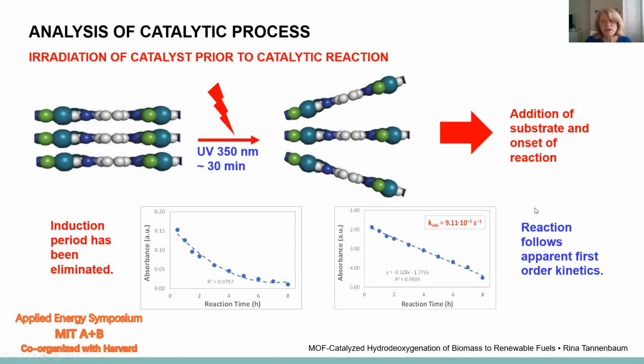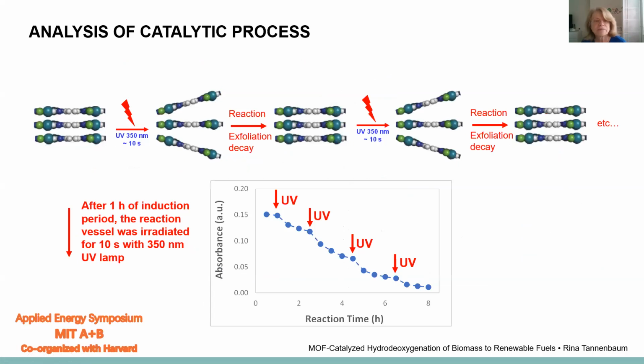And so this is the analysis of the kinetics. So by doing so, we decided, okay, let's look at the following trick. Let's start the reaction as previously. We have the induction period. Just before the end of the induction period, we irradiate for 10 seconds. And then we follow the decrease in concentration.